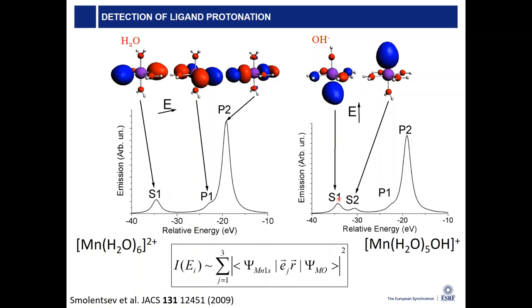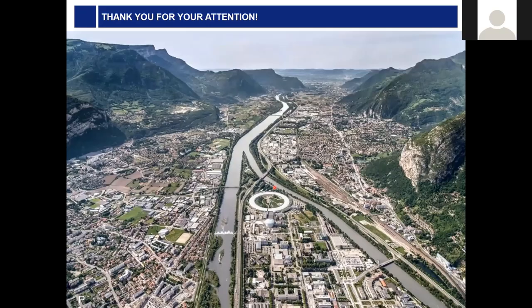So the bottom line here is that this technique allows you to identify the degree of ligand protonation in your sample. But the reasoning, the chemical sensitivity, is always the same. I look at the fluorescence line that is sensitive to the ligand environment, and thus to the binding energy of your ligand molecules. And with this, I thank you for your attention.